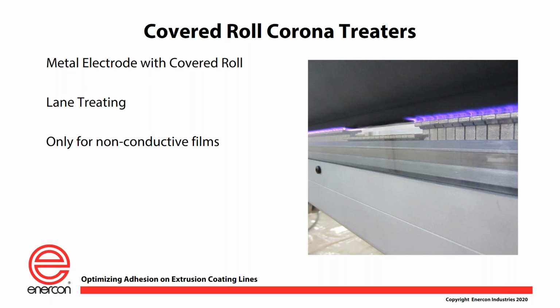Now, as I mentioned before, a covered roll system, which is one of the more basic and original corona treater systems out there, been around for a long time, is just a metal electrode with some kind of dielectric on the roll, which could be a Hypalon rubber roll, a vulcanized silicone roll. More common is a ceramic roll or a silicone sleeve roll. So you've got various coverings that you can put on the covered roll system. The other thing you can also do is lane treat. So you can decal the treatment across your film if you like. And the only drawback with a metal electrode system is you can't run any type of conductive films, meaning you can't run aluminum foil or a metallized PET because you would create a short circuit between the electrode and the ground roll.